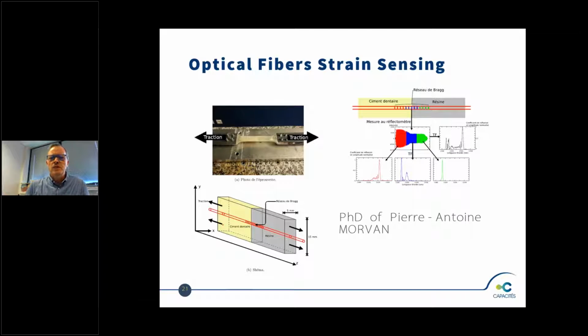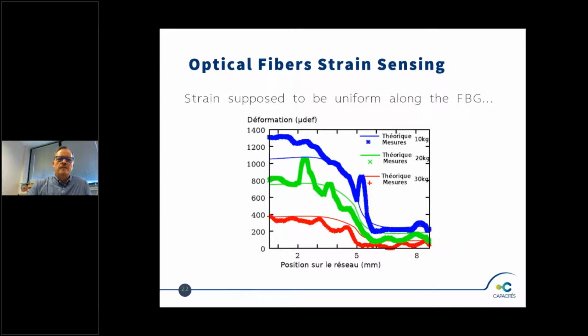So on the right, we have a specific reflectometer measurement. So it's very, very heavy experiment, big interferometers, and this cannot be used in the industry. And from this specific instrumentation, we could prove that when you go from the soft material on the left towards the stiff material on the right, then the strains which are normally plotted as the smooth lines in the theory are not smooth anymore in the experiments. So you suffer from many gradients, many disturbances in the strain field.